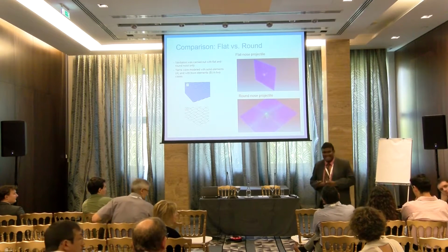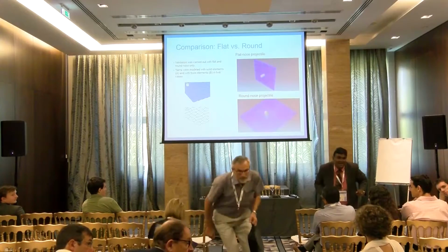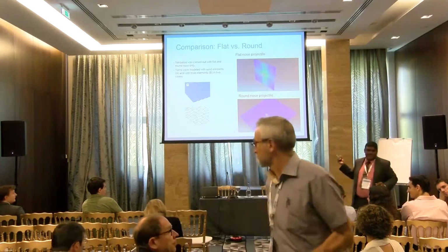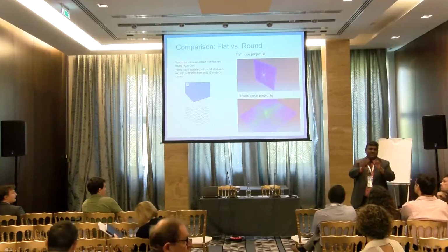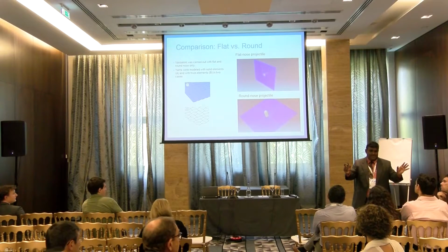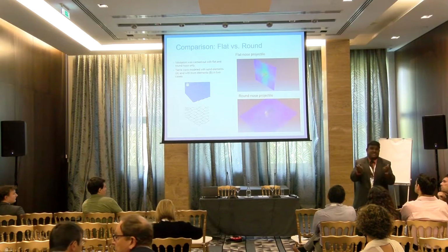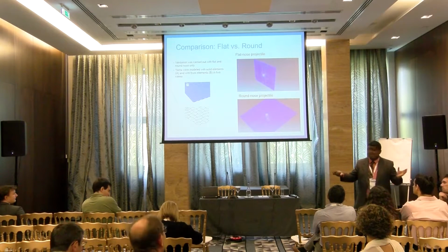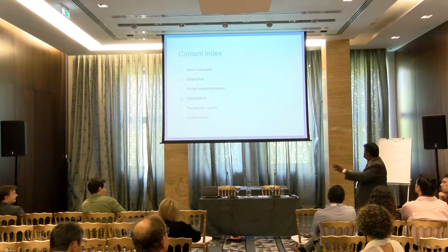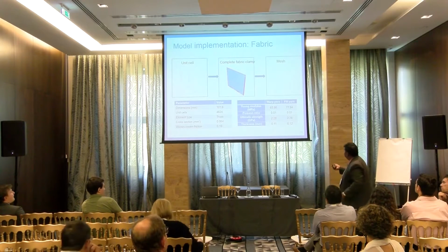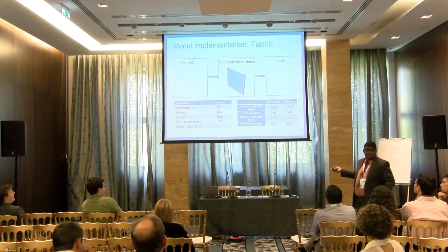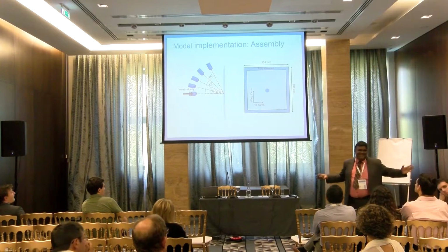Thank you. What kind of failure criterion did you use? What we did, we computed the ultimate strength of the fiber. And we said a fiber fails if its longitudinal stress, which is the stress in the truss element, exceeds the ultimate strength. And the ultimate strength was computed; I put it in a table. Very simple. And it seems to work.